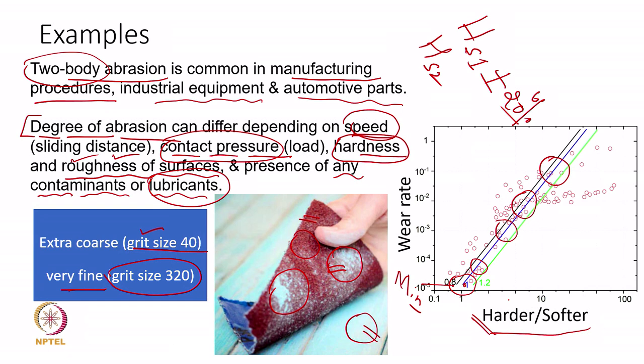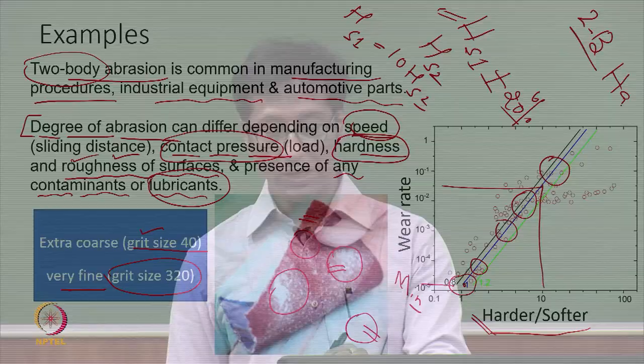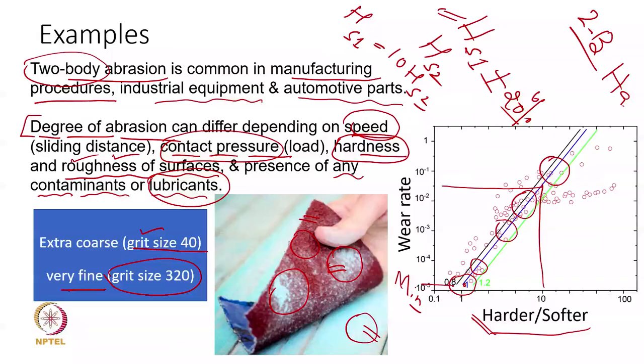So if hardness is increased by 10 times, wear rate may increase by 500 or 1000 times. We need to keep this ratio in account and try to keep the same hardness for soft and hard surfaces in two-body abrasion. So we say 2-body abrasion is controlled by hardness, and this hardness should be the relative hardness: HS1 divided by HS2 should be approximately equal to 1 and should not be very high.